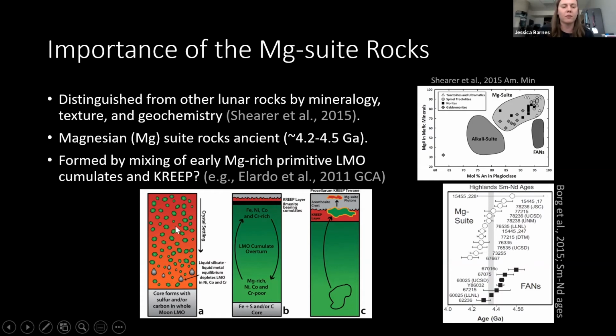So this model from Steve Elardo kind of depicts this idea that they're a mixture of very primitive materials from the mantle and this very residual KREEP layer. And so we think that during overturn, some of those very primitive, early formed mantle cumulates were being brought up close to the surface, or at least close to the base of the crust, and interacting with that KREEP component to form these melts really rich in magnesium, but also rare earth elements.